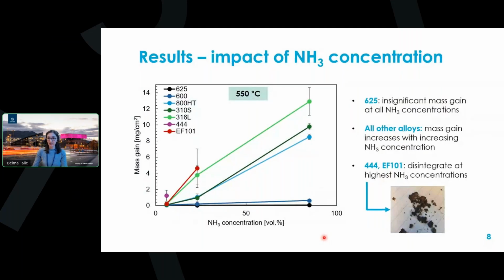To evaluate the nitridation resistance, we recorded the weight of the alloy before and after exposure to ammonia. And generally, we saw that the mass gain corresponded quite well with the extent of nitridation. So the graph here shows the mass gain as a function of ammonia concentration measured at 550 degrees centigrade.